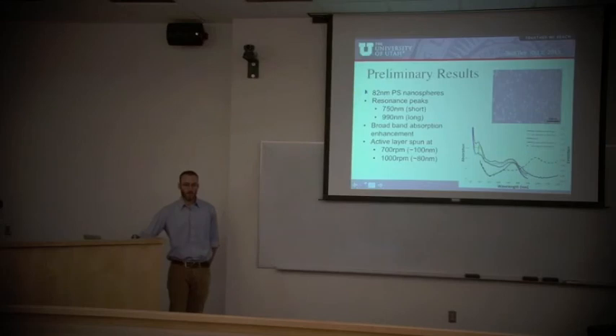Here are some preliminary results. I'm still pretty early in this research, but this is an SEM of the nano crescents which I made. As you can see, it's a pretty uniform distribution of size, and it's nicely dispersed on the surface. And you can see the nano crescent shape. They're not perfect, but they're pretty good. By studying their interaction with light beneath the active layer, I see here that the absorption of the active layer has increased throughout the whole absorption profile of the active layer, where the black line is without any nano crescents, and the red and green are with nano crescents. You can see that the absorption increased.